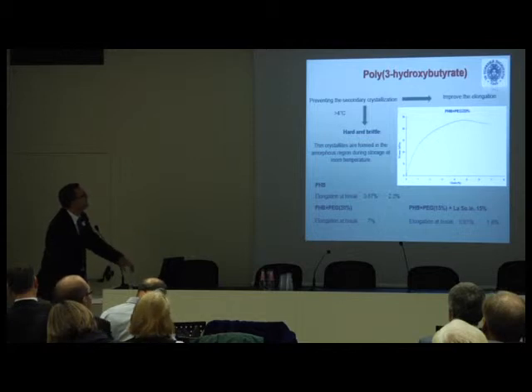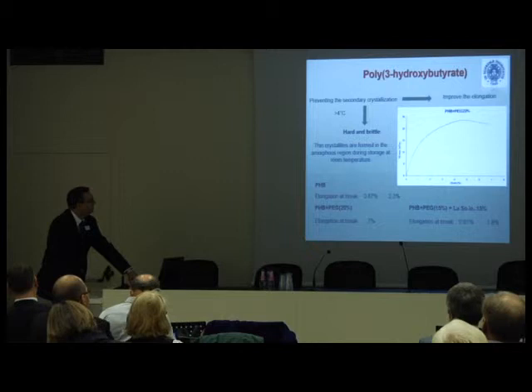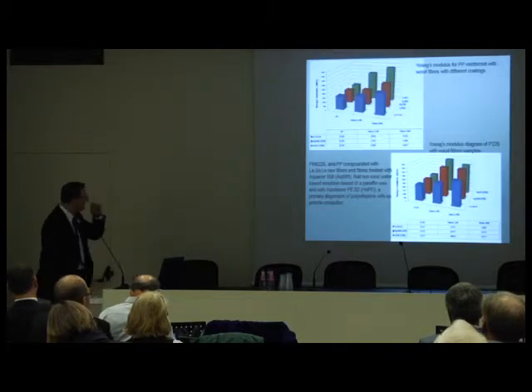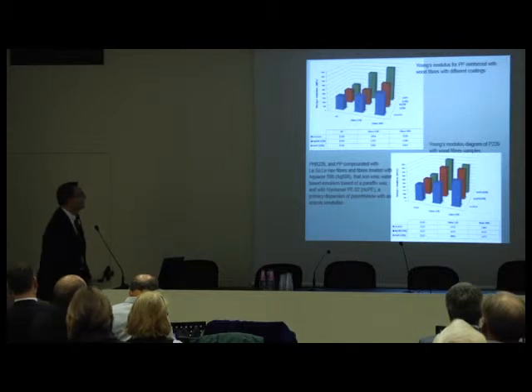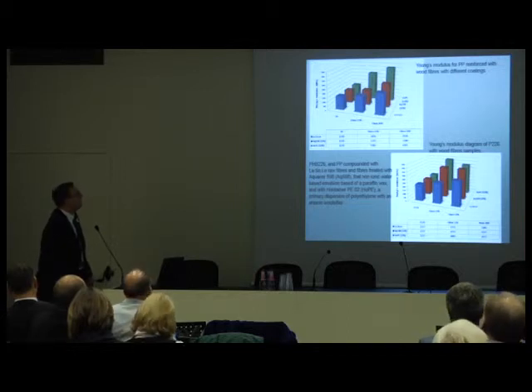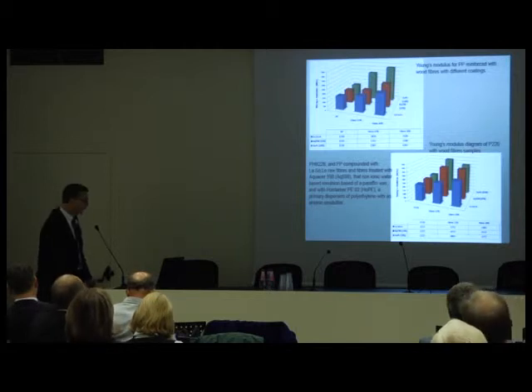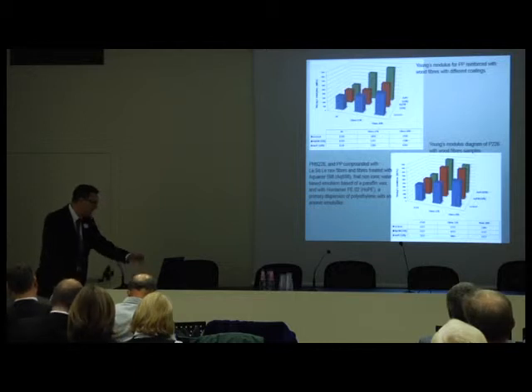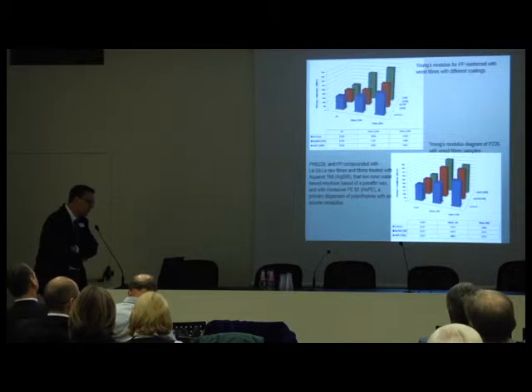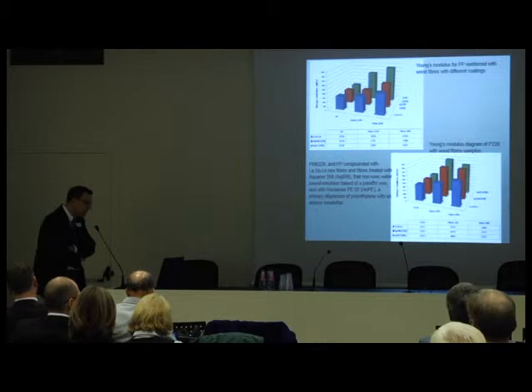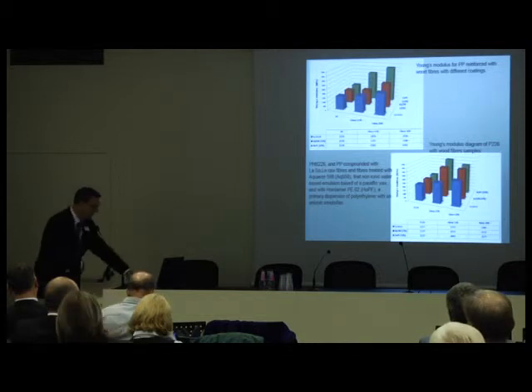So we could go to some application. This, again, is PHB, but I told you that we got some not very good results because the material remains quite brittle even with the addition of PEG. We tried also some other type of coating on the fibers, not just acetylation. We used some paraffinic wax, and on polypropylene composite we improved the dispersion, and also some mechanical properties that you can see were improved. Also, we tested some PHB. This is not the pure PHB. This is a commercial product from Biomer because we found that the blends we could do with PEG were not good enough. P226 is in fact a commercial product from Biomer, which has good properties. So we could use some wood fibers in it, with a good result.